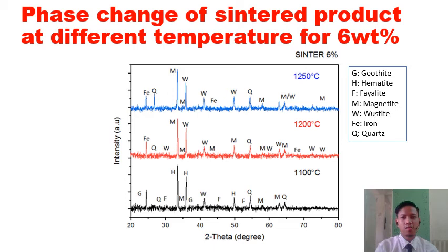This is the phase change of sinter product at different temperatures for 6%, compared to the original composition just now. At 1100 degrees Celsius firing temperature, there is still some goethite that has not been reduced to hematite, followed by slight magnetite phase, wustite, quartz, and also fayalite, which resulted from the bonding of iron and silica. Next, at 1200 degrees Celsius, most of the hematite has been reduced to magnetite phase, and also wustite, followed by slight iron and the existing quartz.